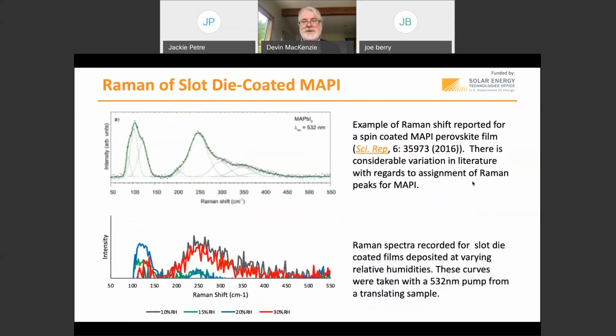Initially, we were interested in Raman because it was also a way to look at multi-step processes. With Raman, we could see the intermediate phases, not just the final phase. And it was a way to probe structure that was compatible with roll-to-roll, because it didn't involve strapping an X-ray source to it. We just needed a reasonably intense laser and some notch filters. But it turned out to be challenging. The noise is much more of an issue, because the Raman signal is relatively low until you hit it with immense powers. But the bigger problem was the variation in the literature with regard to assignment of these peaks. We thought we'd identify lead iodide, intermediate, and perovskite peaks, but there's quite a bit of variation in interpretation of what's going on in the literature.